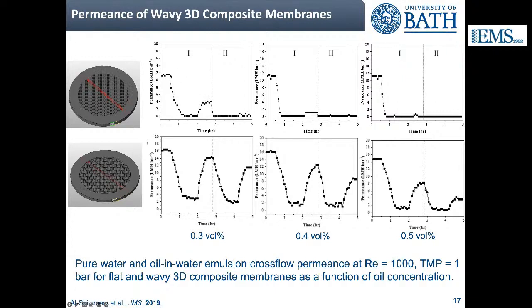One pure water permeance, so you obtain a flat value for the permeance. Then we switch to the oil and water emulsion. You see that the permeance decreases because of fouling. You then reach a plateau of the membrane that is fouled, and then we switch to pure water to clean the membrane, and you can see that there is a partial recovery here, but not all the initial permeance, so there is some irreversible fouling, and then you run the cycle again.